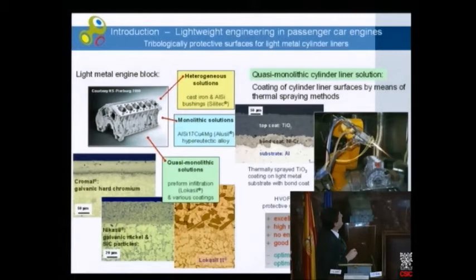And if you look to such a 12-cylinder engine of the present technology, the total weight is not superior to a 4-cylinder engine with 10% of the performance of 30 years ago. And the reason is, it is no more heavy gray cast iron with centimeters of wall thickness. It is an ultra lightweight special aluminum alloy, and just on top, we have a ceramic coating, in some cases with an additional bond coat, and this is the core of the process assembly, where we have again these high stiffness, high precision robots, and you see the torch with this jet, and now we have to think about the best fit of the kinematic arrangement of this supersonic flame spray jet versus our substrate.